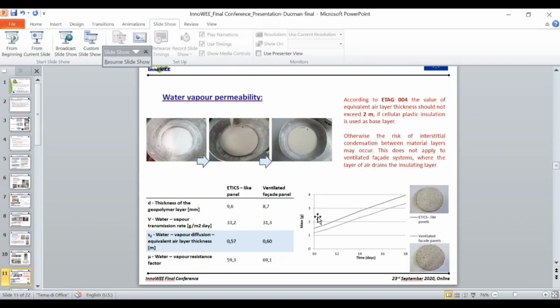For the ETICS-like panels, it's also important that water vapor diffusivity lies in a certain range, because otherwise there is a risk of condensation between layers. In ETAG 004, the water vapor diffusion equivalent, the so-called S value, should be below 2 meters. In our case, for both panels, it's important only for ETICS-like panels, because for the ventilated facade it is not so important, but we tested them in parallel. It's 0.6. So again, we can see that it fits for the intended use in regard to water vapor permeability.